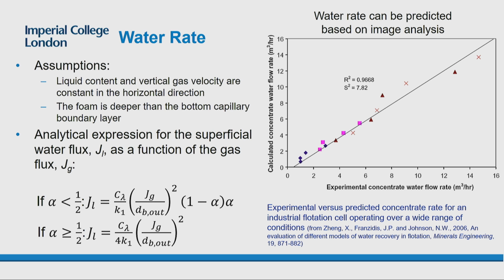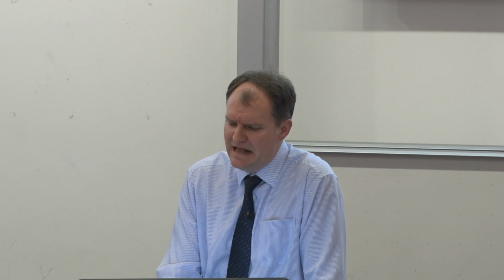But once we'd done that, we could get some analytical expressions, and these were tested on industrial flotation cells by a group at the University of Queensland in Australia, and of all the models they tested, ours gave the best predictions of the overall water rate. That's mainly because the other models being tested were typically empirical models. Basically somebody had done a whole heap of experiments, fitted some curve to those experiments, and then tried to predict the behavior of another system. And the problem is a lot of these relationships hide some of the things that are actually important. So they might measure air rate, and that actually changes bubble size and bursting rate and all these sorts of things. So these predictions often end up bad outside the system they were originally tested for.